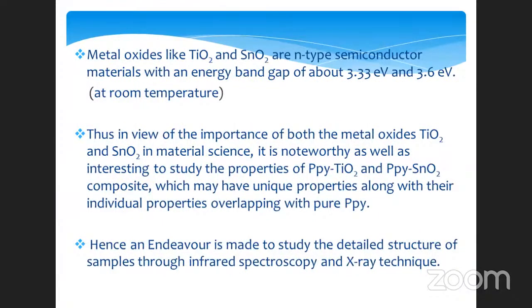Here, my research work is based on the composite formation of TiO2 and SnO2 with the conducting polymer. Why have I used TiO2 and SnO2? Many eminent lecturers have come over here and shown the importance of these metal oxides, which have amorphous nature as well as good conductivity even at room temperature. I have concluded from many reviews that TiO2 and SnO2 have energy bandgaps of 3.3 electron volt and 3.6 electron volt.